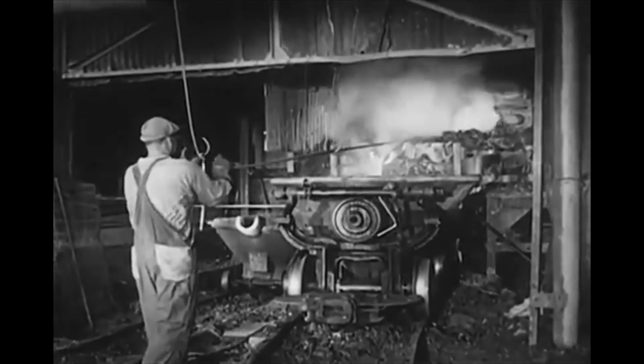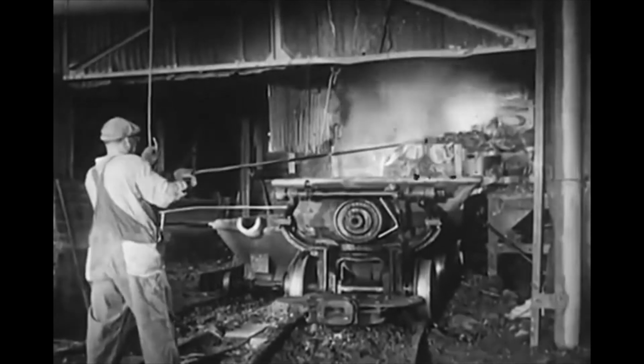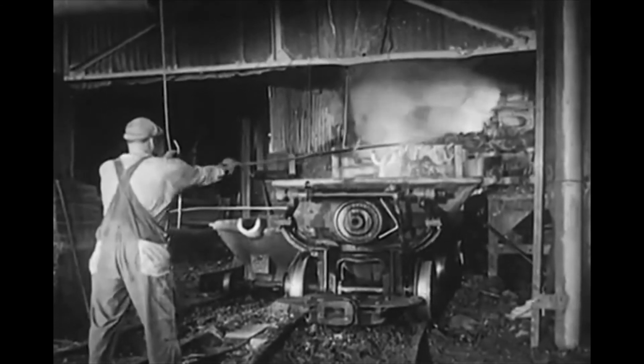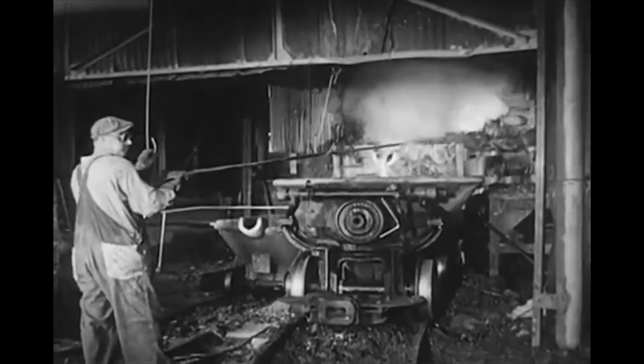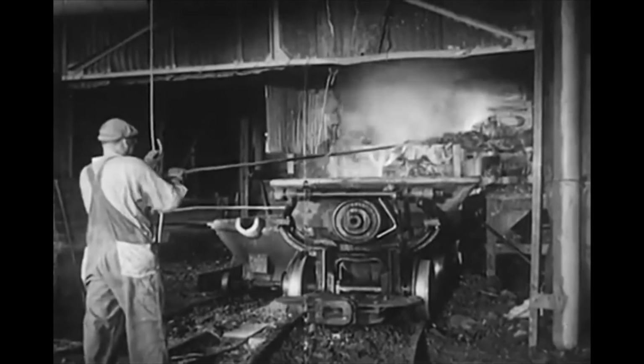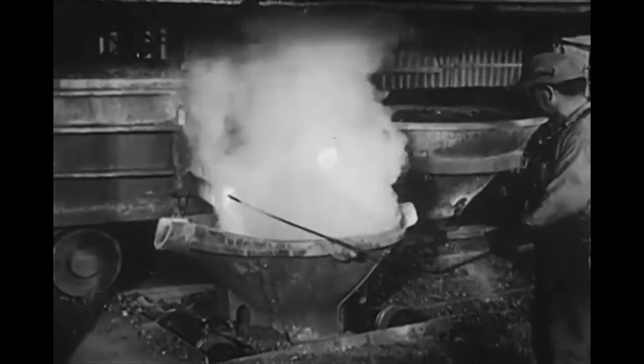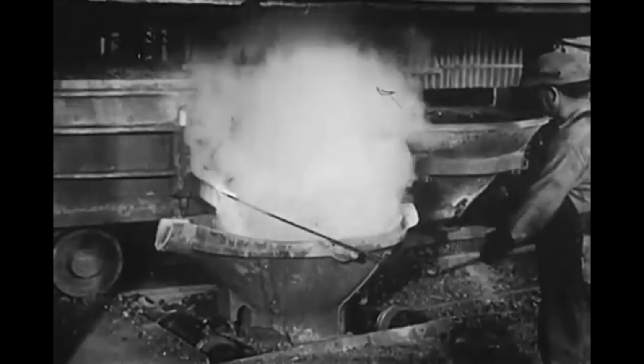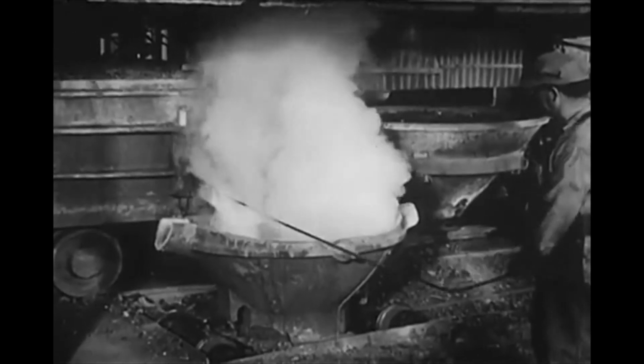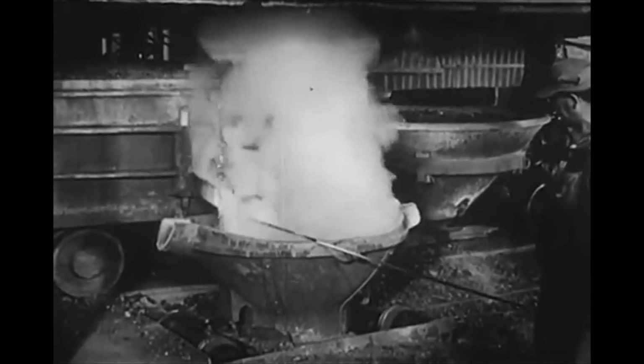The heavy lead, metallics, and matte, a combination of other metals with sulfur, settle on the bottom of the hearth, while the lighter waste product or slag flows over the top and into the slag pot. At the side of the forehearth, the matte is tapped from the bottom and flows into a matte pot. And this is then transported to the granulator.